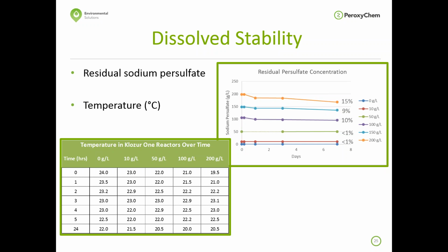The other thing that's very important in terms of dissolved stability is the temperature evolution. PeroxyChem does not recommend mixing our activators with Klozur SP under the classic conditions. This is because we have heard of a few instances where there was heat evolution coming out of those systems after an extended period of time. With Klozur One, we've run a number of studies, and as you can see in this graph, we did not see heat evolution coming out of any of the Klozur One systems.